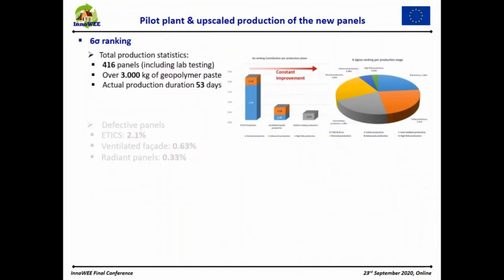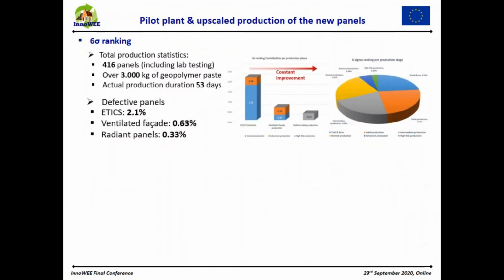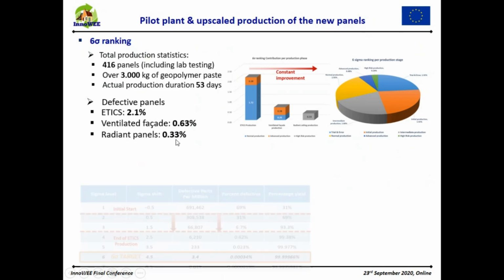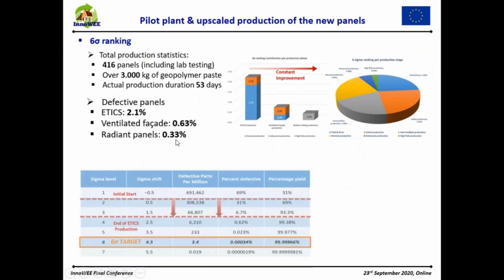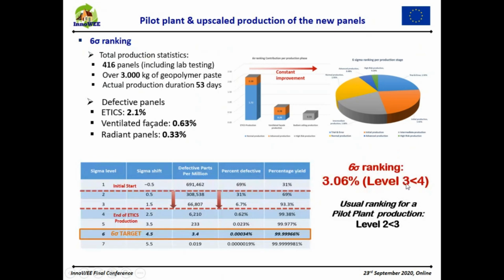And regarding the Six Sigma ranking and the defective panels, you can see here that we had 2.1% defective ETICS panels, 0.63% defective ventilated, and 0.33% defective radiant panels. And regarding the Six Sigma ranking, it was 3.06, so between the levels 3 and 4, and this was a very, very good achievement, as the usual ranking for a pilot plant production is much lower, between 2 and 3.